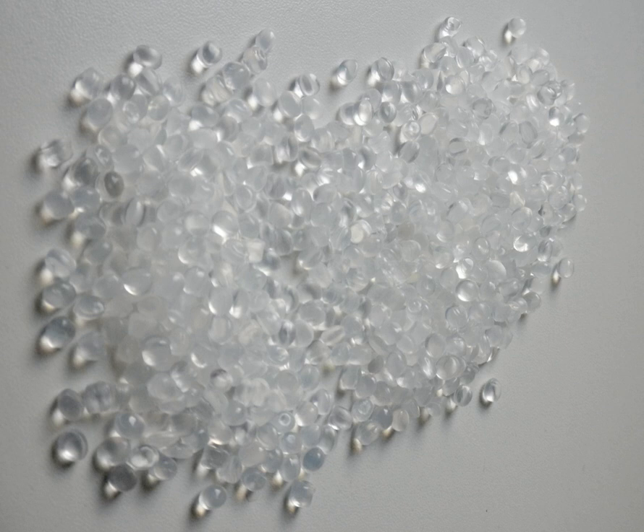Peroxide crosslinking (PE-Xa), the crosslinking of polyethylene using peroxides, e.g., dicumyl or di-tert-butyl peroxide, is still of major importance. In the so-called Engel process, a mixture of HDPE and 2% peroxide is at first mixed at low temperatures in an extruder and then crosslinked at high temperatures, between 200 and 250 degrees Celsius.